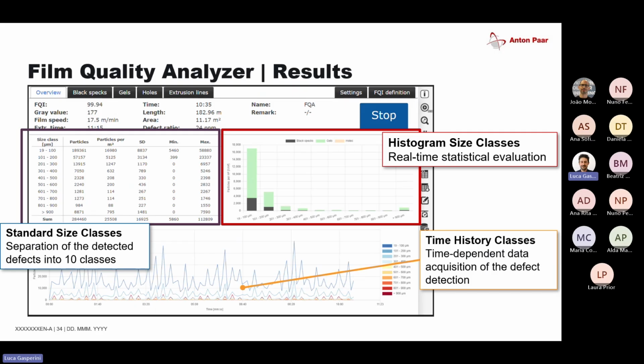So this is how the result of a typical film quality analysis looks like. You get a histogram that lists all the defects classified in different sizes already. You get a timeline of all of the defects, and you could also see when you changed your process conditions in the extruder, it will also translate to the FQA results in case it has an effect on your final product when you change, for example, temperature or screw speed. And then you also have the separation in the different sorts of classes.